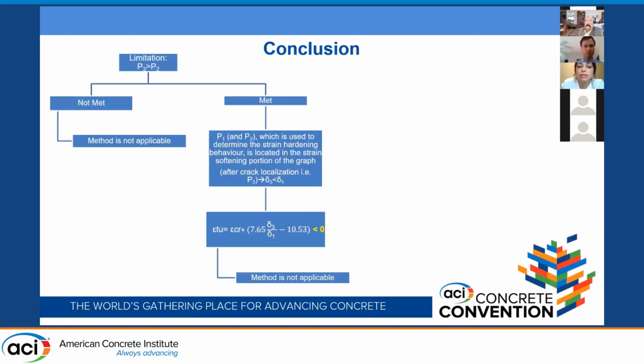And what does this mean? Now when the limit of the code is met, the P1 and P3, which are the 75% and the 40%, are located in the softening branch, which makes delta 3 less than delta 1. And therefore, when we are putting these values in the equation of the inverse analysis, we're getting a negative value, which means the method is not applicable. And whenever P3 is not greater than P2, by default, the method is not applicable.